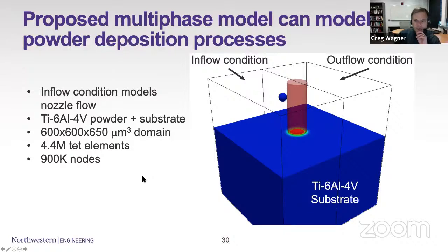So we can use this type of model to look at individual phenomena in, say, a directed energy deposition. Let me show a short example, or a couple of short examples of sorts of things we can do with this, as a proof of concept. We've simulated a moving laser on a substrate and looked at the injection of powder particles above this, not quite at the powder number density that you have for a full DED simulation, but to be able to test the effects of individual powder particles and the phenomena that we see.